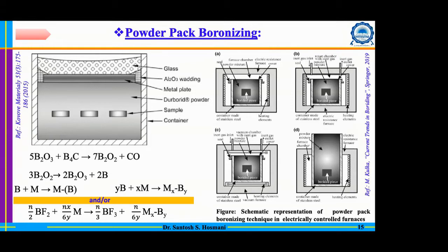Another possibility is the formation of boron halides. These are gases, and these boron halides react with the metal surface and ultimately form a different stoichiometry of boron halide, and then you have adsorption of the boron and formation of the compound. That is another mechanism people have proposed. Now, if you look at the diagram on the right side, you can see that people have used different combinations, and basically they use an electric heating type of furnace, and your combination can be different depending upon what quality of surface you are looking for.